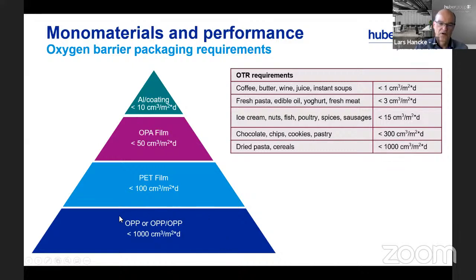Unfortunately, the polyolefins only, like polypropylene or polyethylene, only have poor oxygen barrier properties. So therefore today, usually other films are used like polyester or polyamide, which have better oxygen barrier properties, or we have some specialist coatings, inorganic, organic coatings, or even aluminum layers to have very high oxygen barrier properties. And you see here the demands for certain types of foodstuff. With polyolefins, we can only cover the basic requirements like dry foodstuff, but anything else that you find in this table is not possible with standard polyolefin packaging.